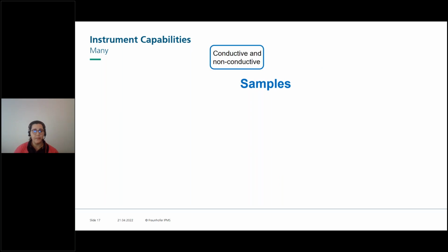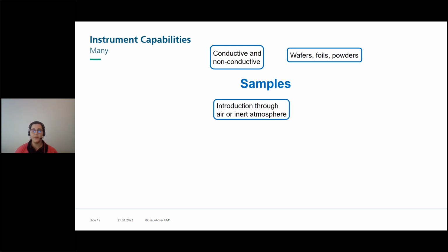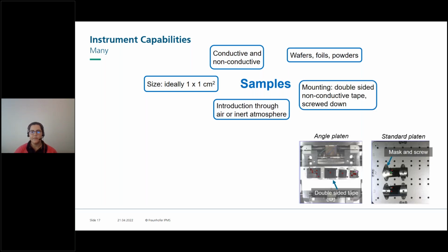The types of samples that we can measure are conductive and non-conductive, wafers, foils, and powders. We can introduce samples through air or inert atmosphere. Ideally, size is about 1 by 1 centimeter squared, but you can also go up to, let's say, 7. But the smaller the sample size, the better, which means you have higher throughput. Samples can be mounted down using a number of ways. For example, double-sided non-conductive tape, as you see here on the left side, or you can also screw them down using a mask and screw on the right side.